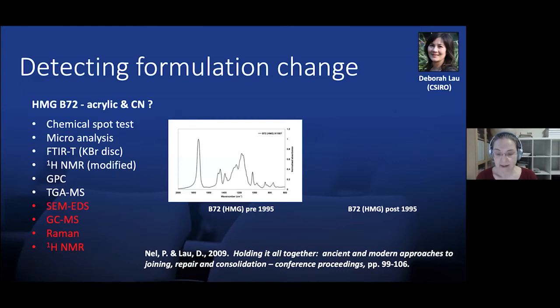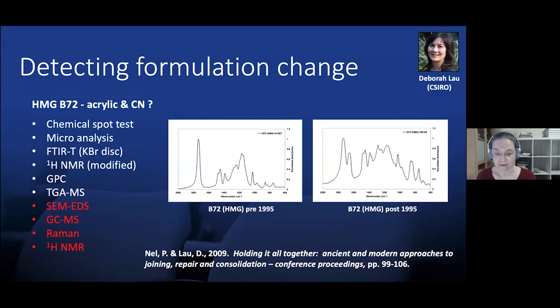Here is the infrared spectrum of B72 before the 95 formulation change, and to the right is the infrared spectrum of B72 after 95 when cellulose nitrate was added. As you can see, this is definitely detectable using FTIR, which in comparison to other types of instrumentation is one of your cheaper options. At the time, I was using a traditional FTIR instrument and traditional sample preparation methods where the sample was ground up with potassium bromide and pressed into a disc.